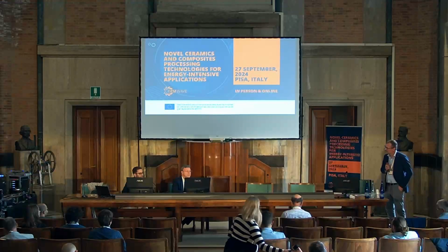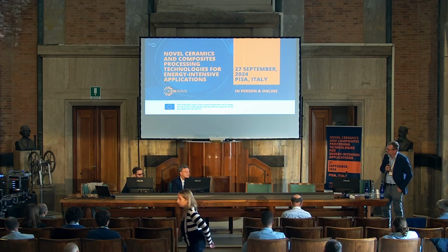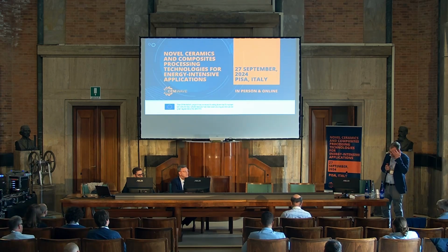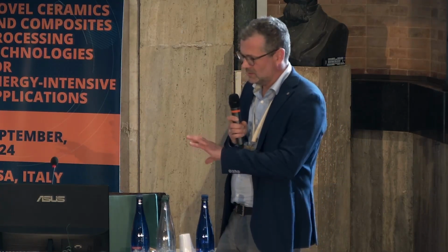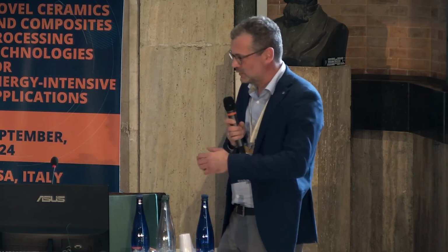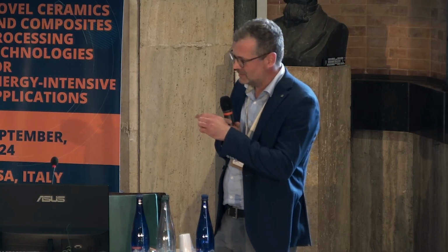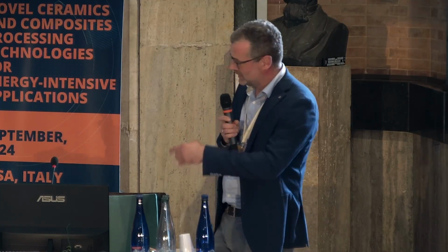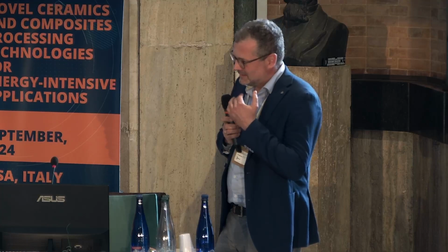My question is regarding the infiltration with epoxy resins. Have you considered some other pre-ceramic polymer like polycarbosilane? What difference do you expect, and what advantages or disadvantages do you see? The thing is, when we use a silicon polymer, which we did not use in this project, you have to put your whole winding machine into a fully gassed atmosphere, both to keep oxygen out and not to burn your polymer off while you wind, because it's very sensitive to air, and this is the main problem.